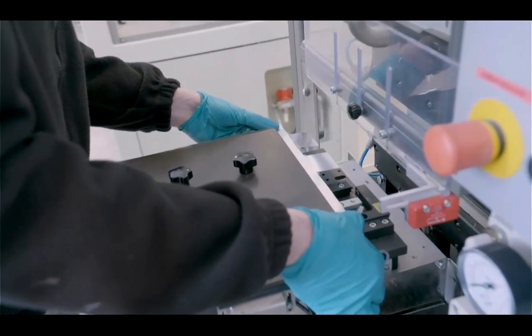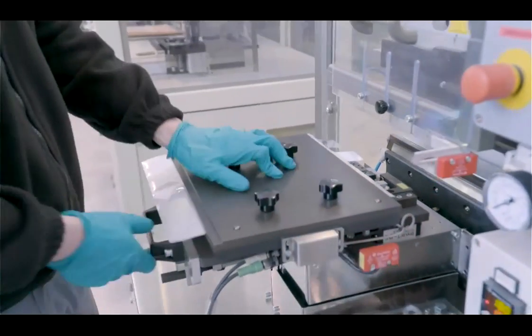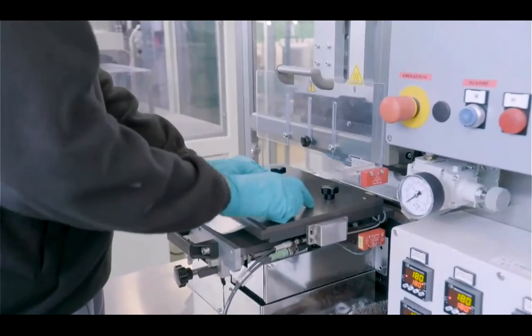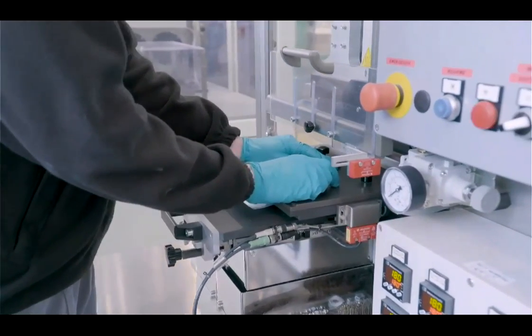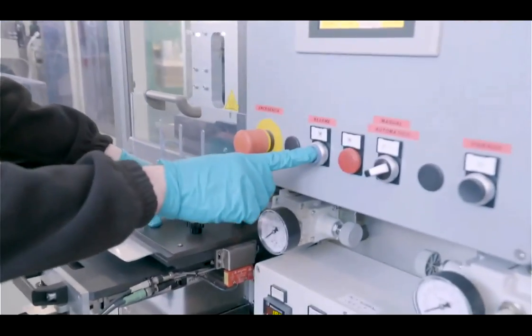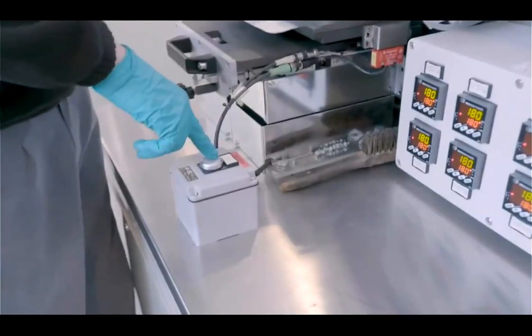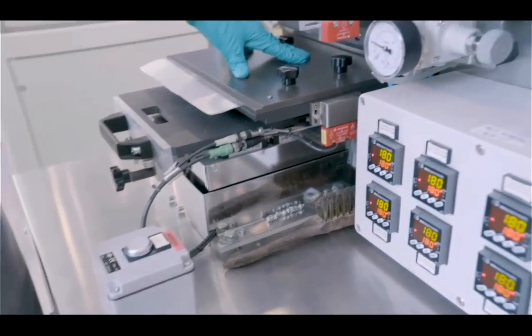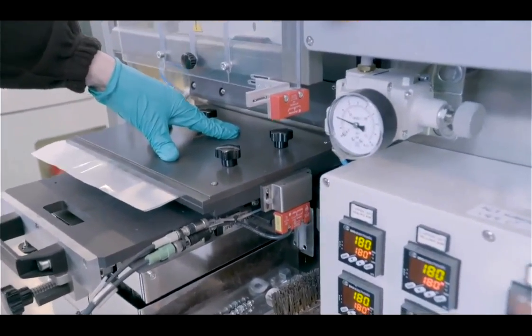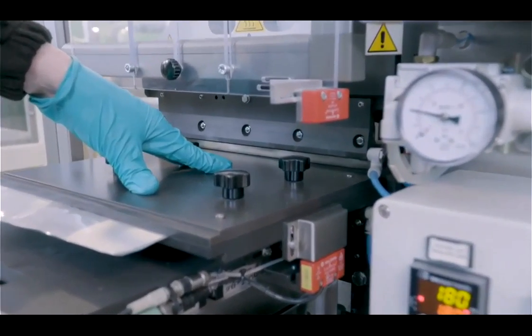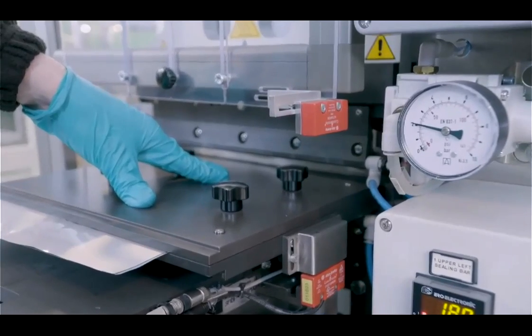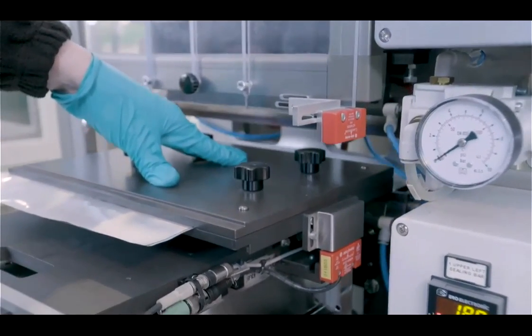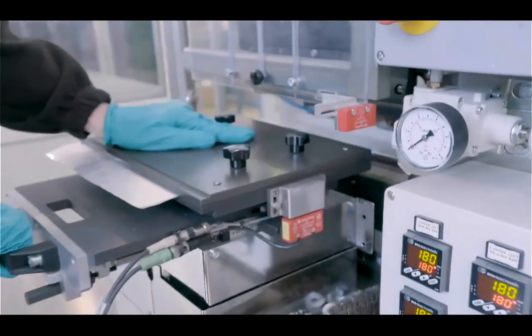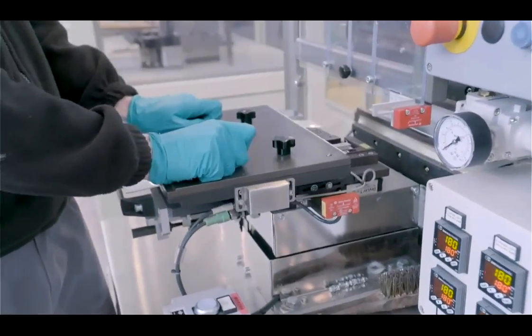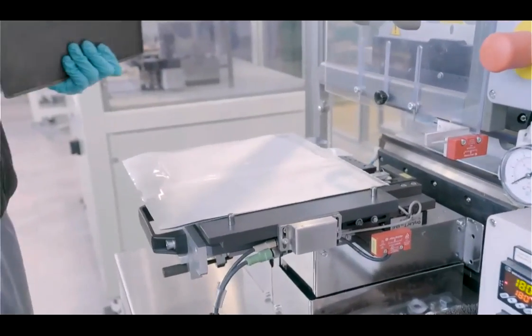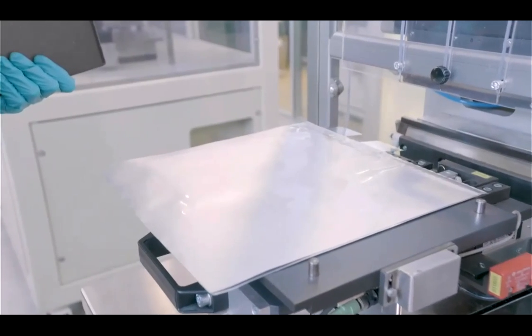The packaging material is aluminum with several layers, 2-3 layers of a polymer. The role of this aluminum foil is to prevent the diffusion of humidity inside the cell. With this machine, we seal 3 sides of the pouch. For the sealing process, we have to adjust the temperature and the pressure we are using. One side of the cell is not sealed in order to be able to fill the electrolyte.